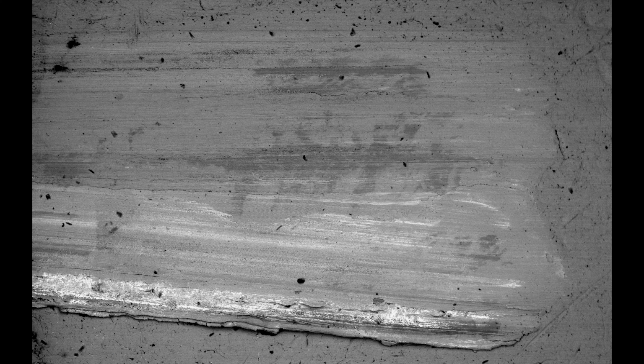And we can see it here, and here, and, well, basically everywhere. So in my tests with the guns I used, the rifling dug through that thin copper coating and dragged across the steel part of the jacket at 1,000 feet per second. We can see it pretty dramatically here if we look at the whole fired bullet from the outside. Here's the mark from the rifling. Here's the copper. And showing through, we can see the steel.